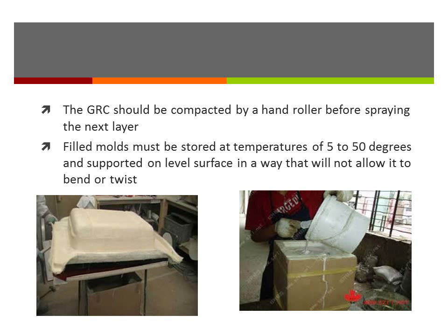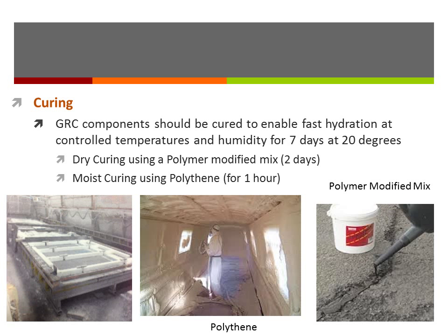The GRC should be compacted by a hand roller before spraying the next layer. Filled molds must be stored at temperatures ranging from 5 to 50 degrees Celsius and supported on a level surface in a way that will not allow the component to bend or twist.